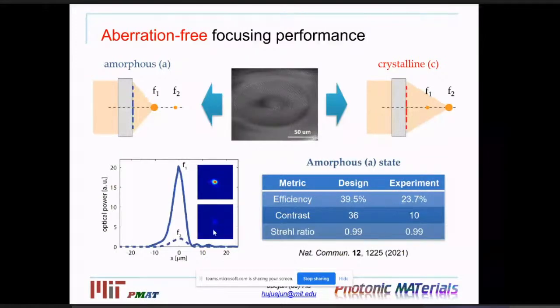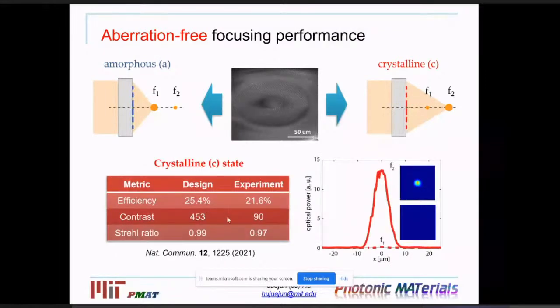And we also realized that we can have very high quality focusing with very large contrast between these two states here. And the focal spot is also at the diffraction limit, indicating that this lens creates essentially no optical aberration during the reswitching process.